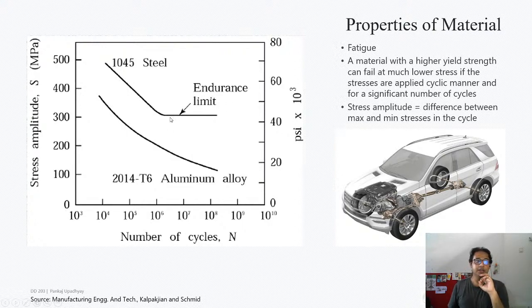So that is why we use materials which show a property of endurance limit. Here this is for 1045 steel, a type of steel which shows an endurance limit. If you apply a cyclic load of 300 megapascals, the amplitude being the maximum stress applied in the cycle, you can go on indefinitely. The material will not fail because it has an endurance limit just above 300 megapascal. If you take, however, a cyclic load of, let's say, 400 megapascal, it will definitely fail after so many cycles. So this is fatigue strength.